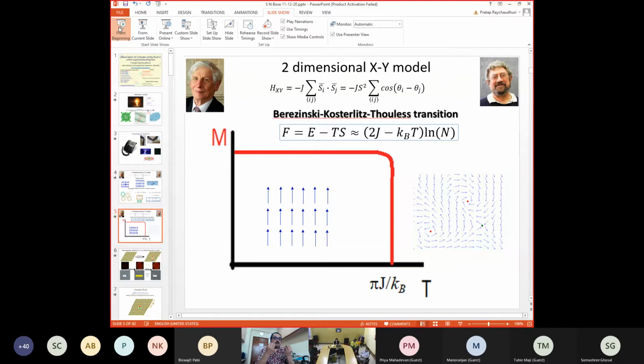So if I decrease the free energy by creating one vortex, I can also create two vortices and three vortices and so on, which means that I will have a sudden proliferation of vortices, and my magnetization will suddenly crash to zero. When I am plotting this magnetization, I am assuming that each of these spins has some magnetic moment associated with it. So here in the ordered state, I had a finite magnetization, and that magnetization has suddenly crashed to zero. Now, whenever you have this sudden jump in, let's say, something like magnetization, you tell yourself that this is a first order phase transition. We know that in a first order phase transition, an order parameter has an abrupt jump. But this is where